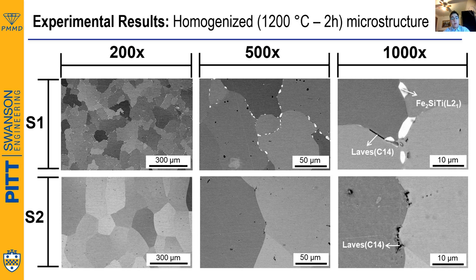Here again, you have another set of backscatter SEM images of S1 and S2 at 3 different magnifications detailing the homogenized microstructure. We see that these images show a slight disagreement with the predictions that CALPHAD made. After 2 hours at 1200 degrees C, S1 does have a minimum amount of Laves and MX as predicted, but to our surprise, the grain boundaries are decorated with a white color L21 phase, something that CALPHAD didn't account for. S2, on the other hand, shows a cleaner and more uniform microstructure, but a minimum amount of as-cast retained Laves continues to show up.